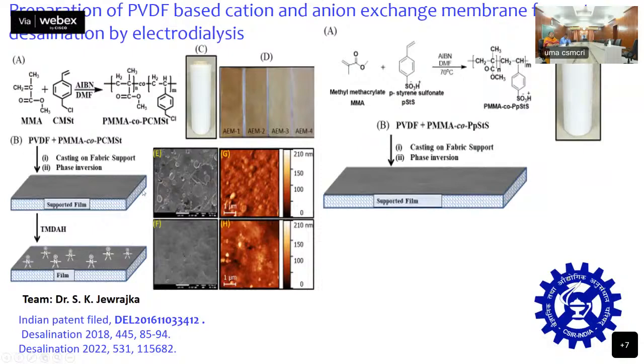So now we also have membranes which have been prepared by the solution casting method. We have prepared PVDF-based cation and anion exchange membranes on fabric support for water desalination by electrodialysis as well as by diffusion dialysis. So the anion exchange membrane is prepared from the polymer of methyl methacrylate and chloromethyl styrene, and then the polymer is mixed with PVDF in the ratio of 30:70 weight by weight and cast on non-woven fabric by immersion process. And then the functional group is introduced in the membrane by treatment with tetramethyl diamino hexane.